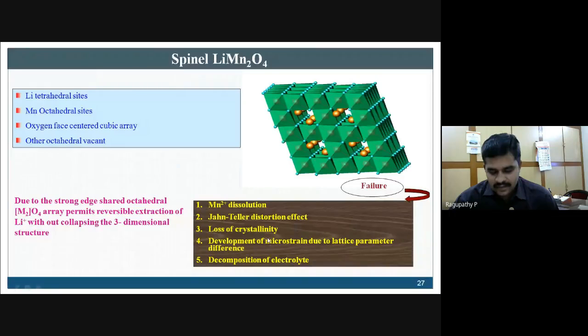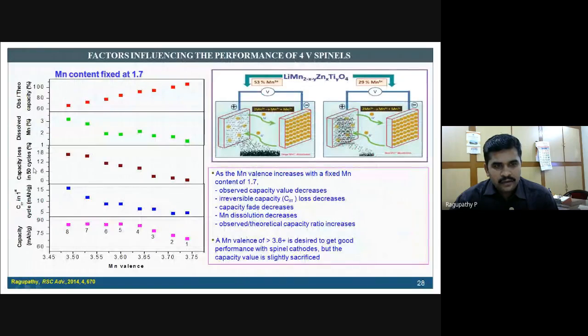So how do we address these things? We have taken this compound and tried to address some of these factors. We mainly focus on the dissolution part. Okay, don't worry about the calculation and other things. The point I'm trying to tell you is that here it is only the amount of valence. When you look at these two cartoons, when you have more than 50% manganese 3+, the dissolution is more. When you have around 30%, you could see minimum dissolution.